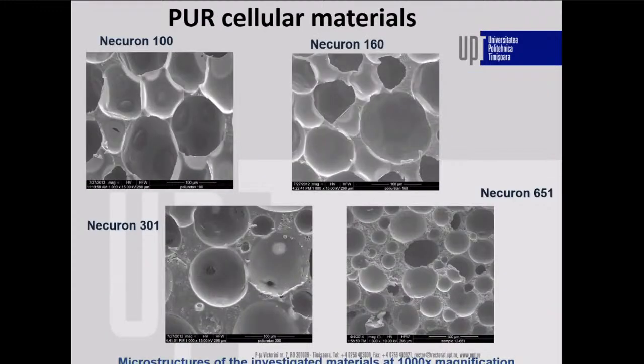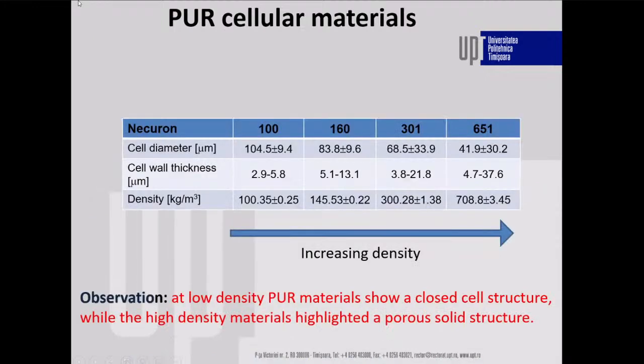What I will show you today are 4 different types of polyurethane foams with the commercial name Necuron. They are made in Germany by the Necumer company, starting from 100 kilograms per cubic meter density up to 700 kilograms per cubic meter density. You can see here that with increasing density, the cell diameter decreases from 100 microns to around 42 microns.